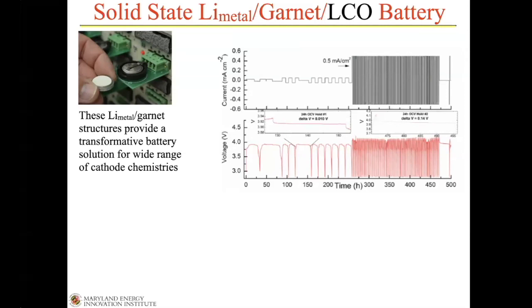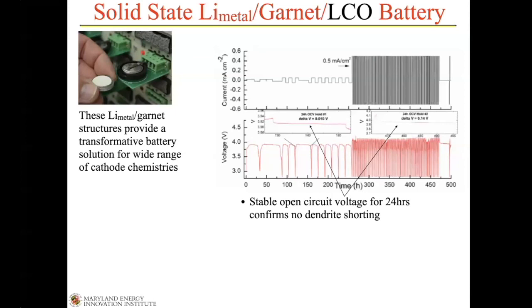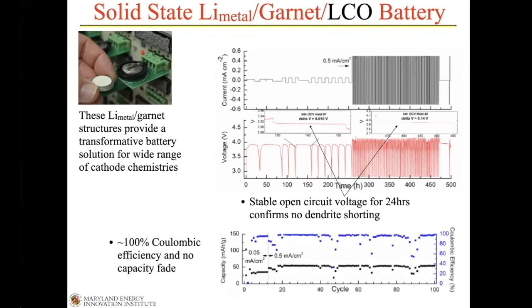I'd also want to point out that we had a couple of different holds for 24 hours to demonstrate that it held 100% state of charge with no voltage decay, again confirming no dendrite shorting, both at the initial cycling and at the end of the 400-something hours of cycling. The corresponding coulombic efficiency and capacity is shown here. Again, no capacity fade. This is one of our earlier cells, it was a little bit more noisy, but again demonstrating the ability for this type of technology to cycle with a lithium cobalt oxide cathode and lithium metal anode.